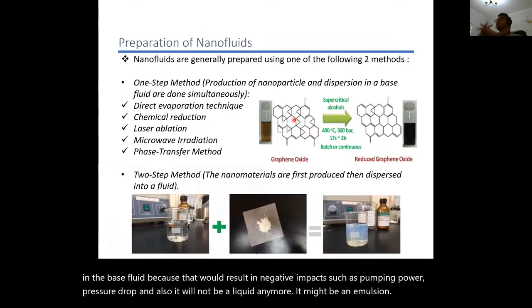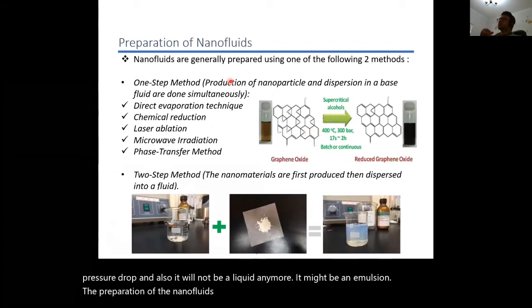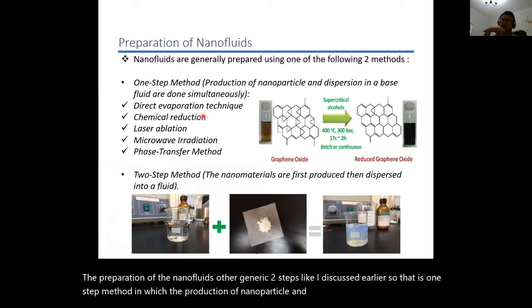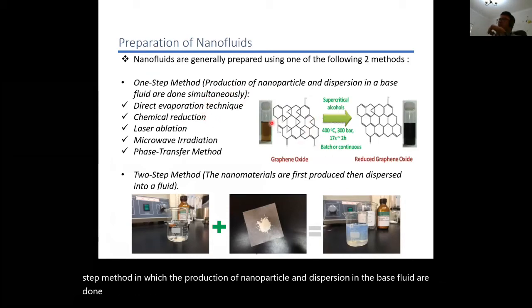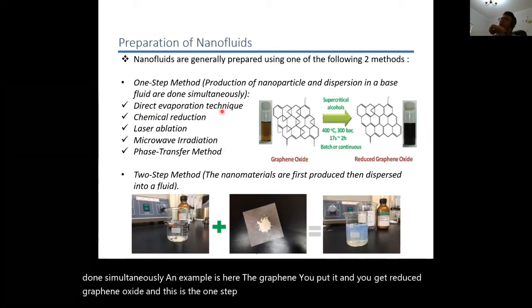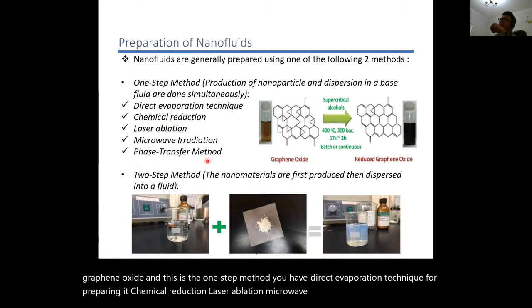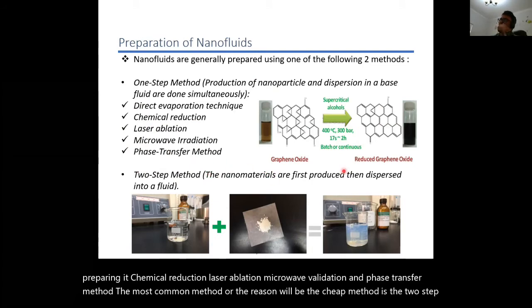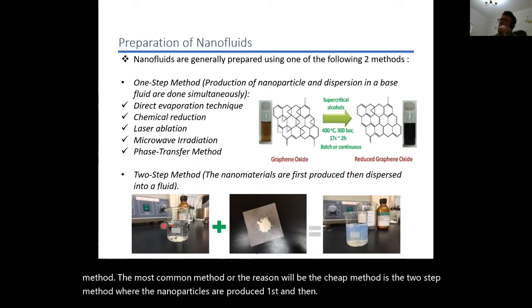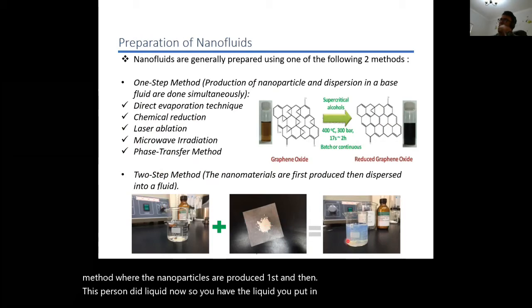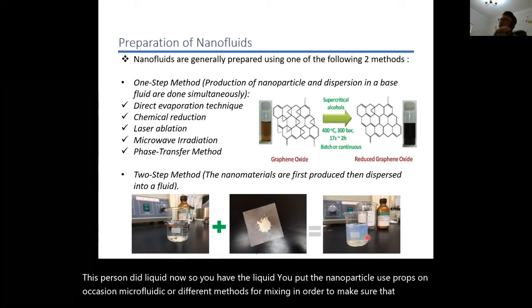For the preparation of nanofluids, there are generally two steps, like I discussed earlier. There is the one-step method, in which the production of nanoparticles and dispersion in the base fluid are done simultaneously. An example is graphene: you put it in and you get reduced graphene oxide. This is the one-step method. You have the direct evaporation technique, chemical reduction, laser ablation, microwave irradiation, and phase transfer method. The most common method, because it is the cheapest, is the two-step method, where the nanoparticles are produced first and then dispersed into the liquid. So you have the liquid, you put in the nanoparticles, and you use probe sonication, microfluidics, or different methods for mixing in order to make sure that the nanoparticles are suspended.